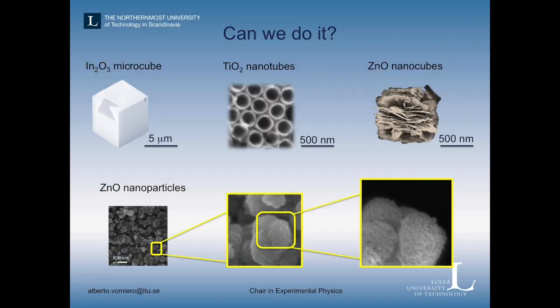And that's very important because in solar cells, for instance, the absorbed light is proportional to the specific surface of your material. It means that you increase the light absorbance by a factor of roughly 5,000. Okay, and that really works. So are we able to do this division of materials and to create new nanostructured materials? Luckily the answer is yes. Then it comes to the problem with the functional properties of these materials. And in fact we can create nice shapes of different compositions. Here we have indium oxide microcube, here we have titanium oxide nanocubes and nanotubes, so we have zinc oxide cubes, and you can see that there is a nanostructure in them, so you're easily able to produce, let's say, 20 nanometer nanoparticles aggregated together and forming a well-structured material.